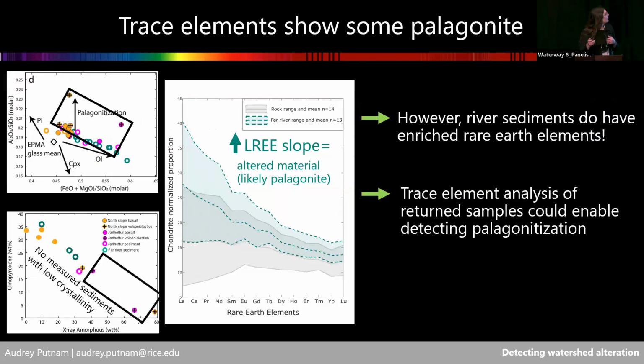When we turn to trace elements, it gets a little bit more complicated, and we might be starting to see a little bit of evidence for that. I'm showing here chondrite normalized proportion across rare earth elements. In gray, that is the range and mean of the watershed rocks. And then green, that is the range and mean of those river and sediment samples. And we have a lot more here than we have for the XRD. And we can see that overall, the river sand samples are enriched in rare earth elements, and especially in the light rare earth elements. And this is potentially consistent with some amount of palagonitic alteration being preserved in this. So this is an example of something that we might not be able to differentiate with bulk XRF or XRD at rover scale on Mars.